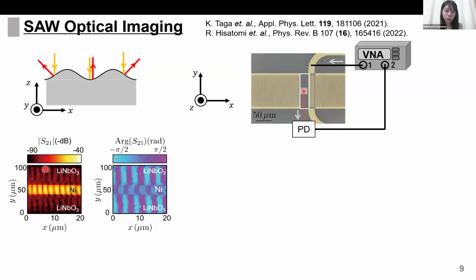In the X direction, amplitude peak positions have an interval of 2 micrometers, and the phase inverts by pi every 2 micrometers. In the Y direction, the nickel film does not have the phase node. So standing waves with wavelengths 4 micrometers, or fundamental waves, were confirmed in the nickel film. So I have confirmed the mode. We now evaluate the surface acoustic wave mode volume.